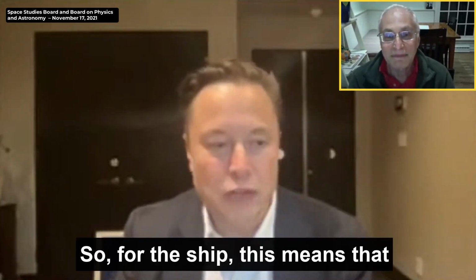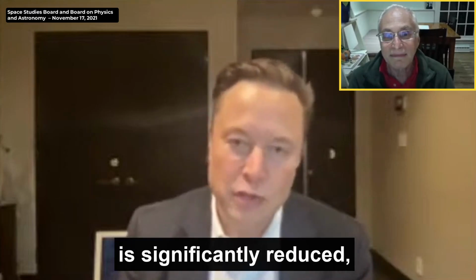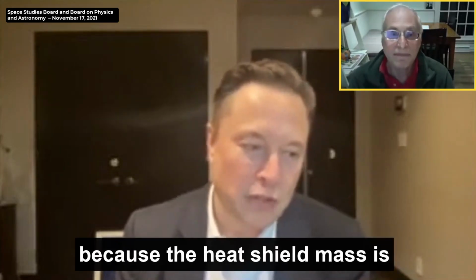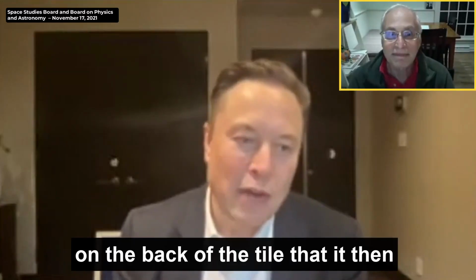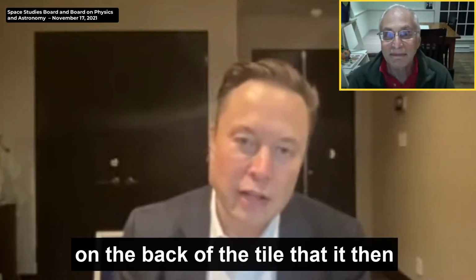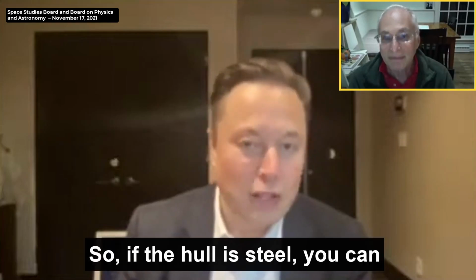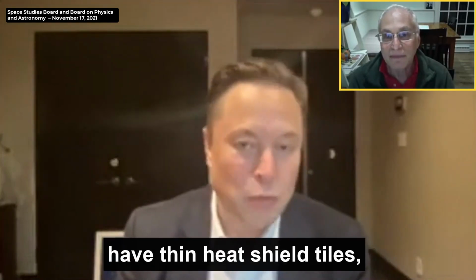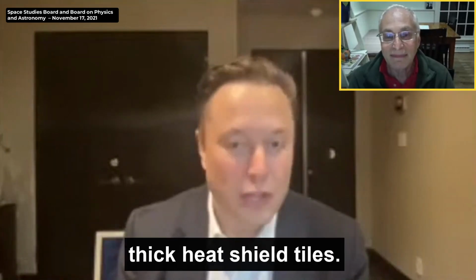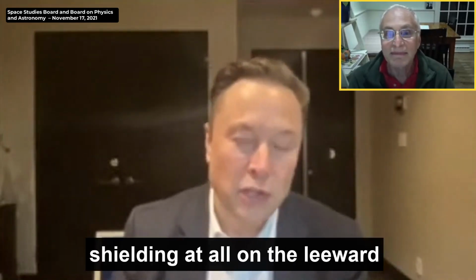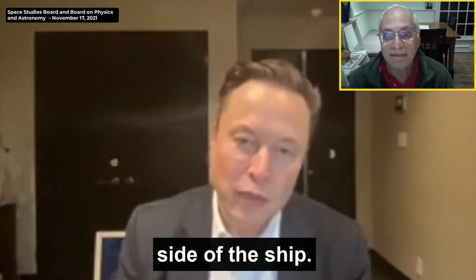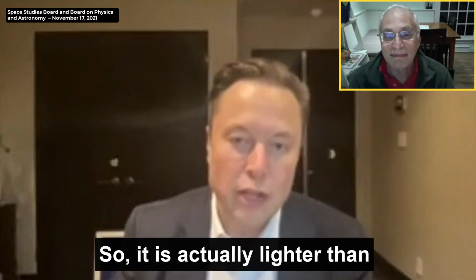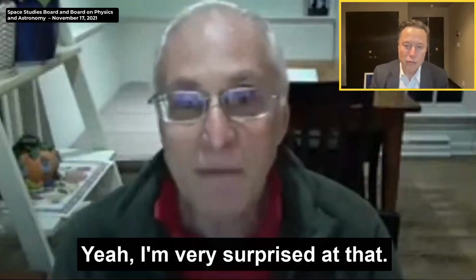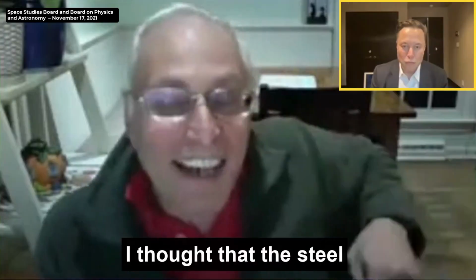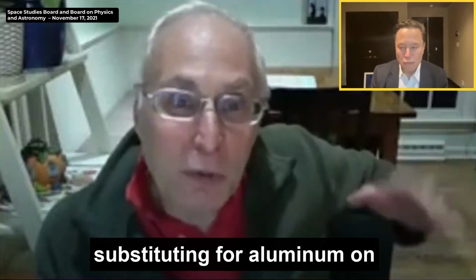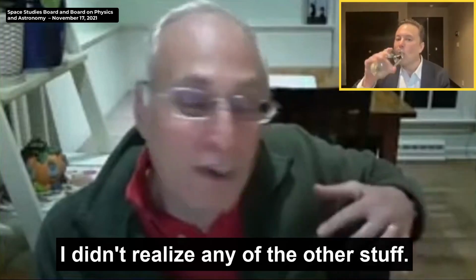So for the ship, this means that the heat shield mass is significantly reduced, because the heat shield mass is determined by the temperature on the back of the tile that then transmits to the hull. So if the hull is steel, you can have thin heat shield tiles, whereas if the hull is carbon fiber or aluminum, you have to have thick heat shield tiles. And you also need no heat shielding at all on the leeward side of the ship. So it is actually lighter than the most advanced carbon fiber vehicle. Yeah, I'm very surprised at that, but that was very, very interesting. I thought that the steel substituting for aluminum on reentry made some sort of sense. I didn't realize any of the other stuff.